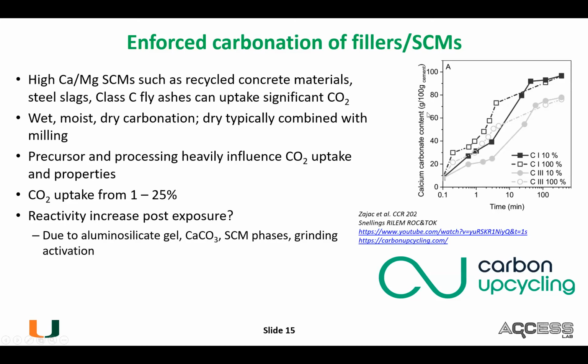I've seen studies in wet, moist, and dry conditions. But the dry typically is combined with some sort of milling or grinding process as well, like I've described earlier. So the precursor and processing heavily influence the CO2 uptake - anywhere from 1 to 25% is possible.